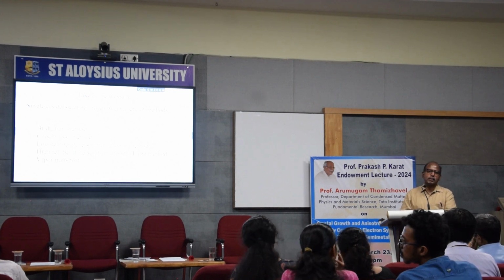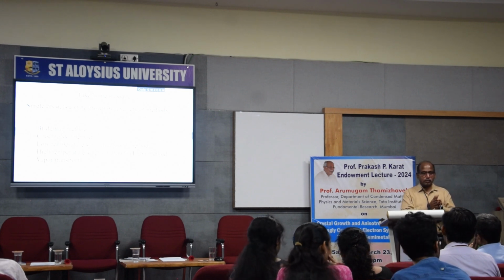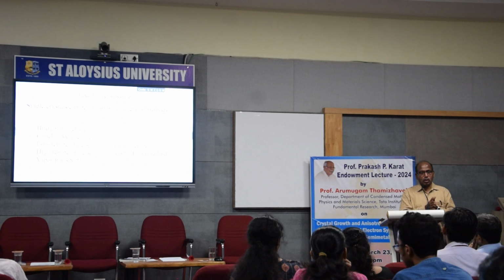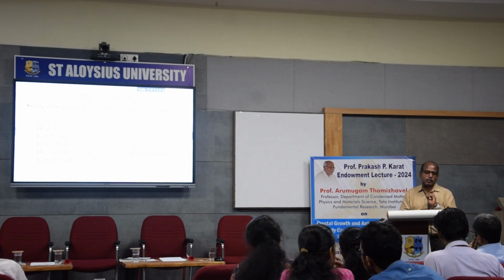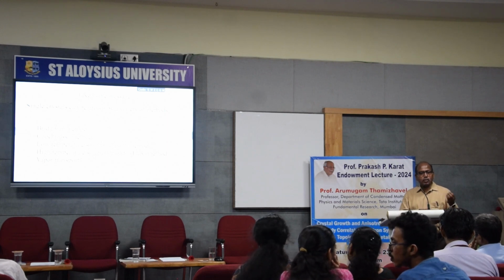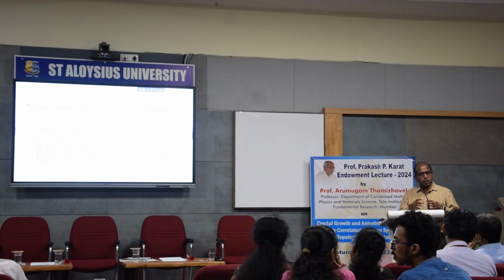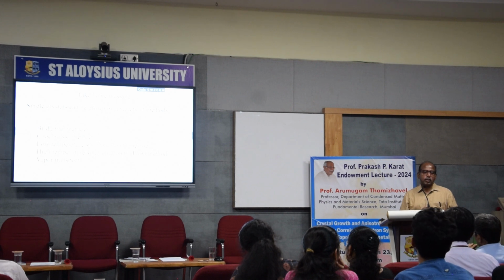Powder X-ray diffraction. Single crystal XRD we are using only for finding the crystallographic direction. That means we are using the Laue method. Single crystal X-ray diffraction is used to solve the crystal structure, but we are not interested in solving the crystal structure. Our aim is to find the crystallographic direction. We are growing the crystal and we don't know which crystallographic direction is there, so we use the Laue diffraction method to find out the orientation of the crystal and cut the crystal.